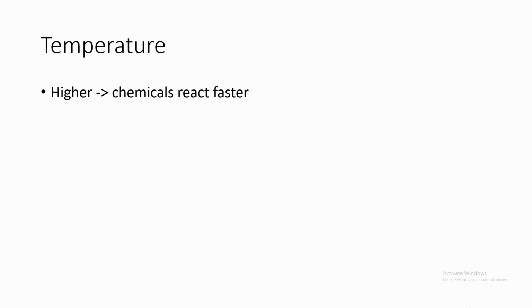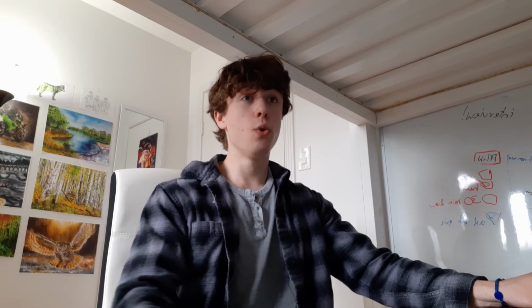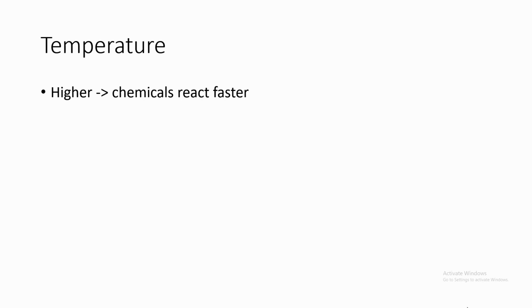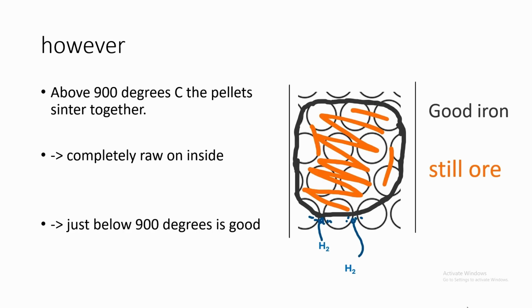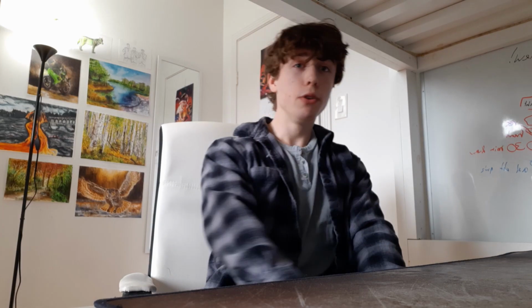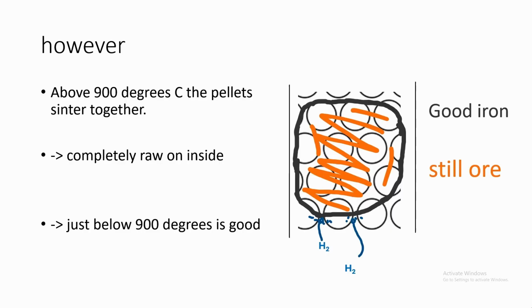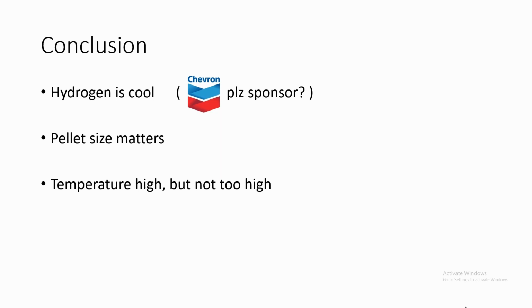Now, temperature. If it's higher, the chemicals react faster. Who would have thought? But if you turn the temperature too high, above around 900 degrees Celsius, it doesn't melt, but the atoms on the surface of the pellets fuse together because of sintering. Sintering is like almost melting, but just on the outer surface of the pellet. Overall, it causes the pellets to clump together and form a dense, homogeneous mass, which doesn't let hydrogen through. So the outside gets reduced, but the inside is still completely undercooked. In total, hydrogen is great, the pellet size is important, and the temperature should be high, but not too high.